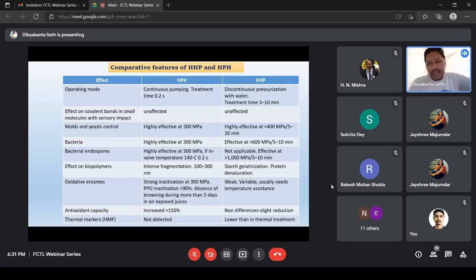In high hydrostatic pressure it is also ineffective, because the covalent bonds are not broken, so we are not breaking the secondary or primary structure of the protein. Molds and yeasts are highly affected at this pressure. Bacteria are highly affected compared to hydrostatic pressure. Oxidative enzymes are strongly inactivated at more than 300 megapascal. Antioxidant capacity increased by more than 150%. That means we need not provide any additives to give antioxidant or antimicrobial activity to the food materials. In that way, we can say that the product produced by high pressure homogenization is a clean label food. Thermal marker, as I have mentioned, is not yet detected or researched.